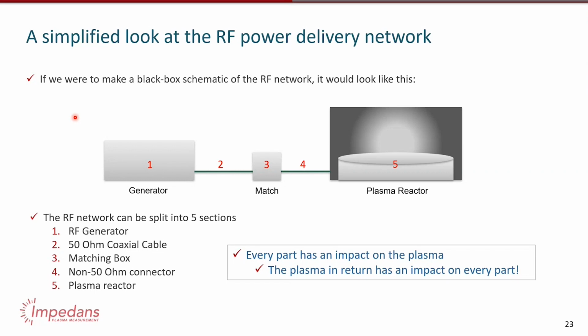If you're looking at data fast enough, you'll actually start to see these things you wouldn't normally see, or you'd see that it's very noisy and there might be small levels of arcing happening in the match or happening in the tool. So the answer is actually yes. By measuring at different points, you can learn where an issue is. So for example, I have data which I can't show now, but I could show on a call, where we could see that arcing was happening, and then by changing the measuring point, we determined that the arcing was happening inside the matchbox as opposed to inside the plasma chamber.